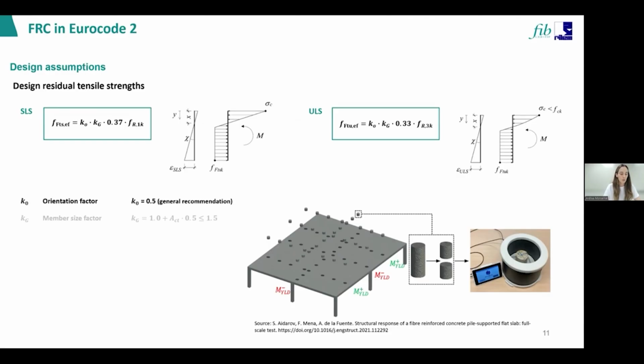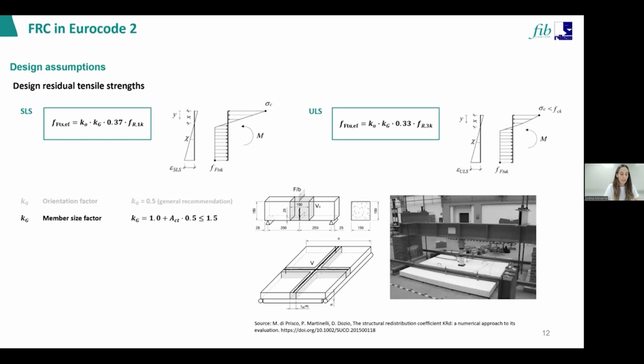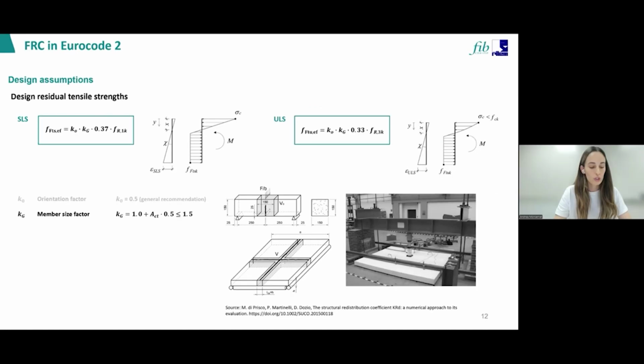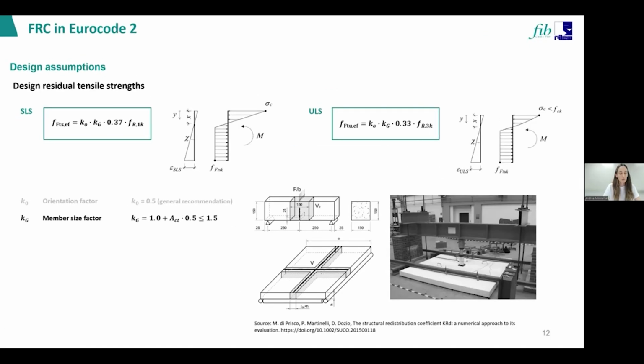on the real structure. Actually, in the example that you see, in this experimental campaign, a full-scale steel fiber reinforced concrete flat slab was tested up to failure, and afterwards, cores were extracted from the slab and were analyzed using inductive techniques to characterize the fiber distribution and orientation within the structure. But Annex L also considers the influence of the structural size on the variability of residual properties through the member size factor. This allows considering a more stable structural response in large scale members.